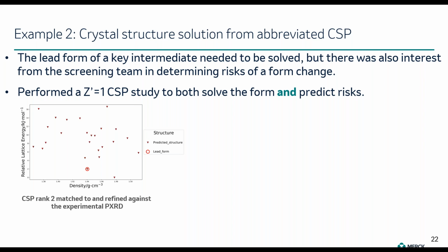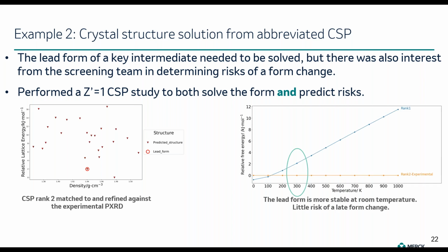The crystal structure ranked second in lattice energy, had a very good match with the experimental powder pattern, and could be easily refined against it, and this allows structural solution. Since it was predicted to be metastable in lattice energy, we went into free energy calculation, and we noticed that at room temperature, at 300 Kelvin, this crystal structure becomes actually more stable. So there is little risk of a late form change at room temperature.